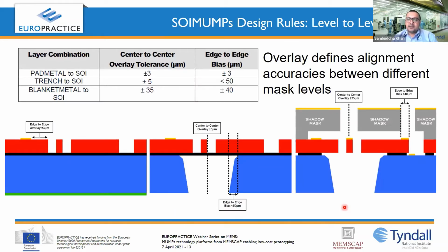There are also some level to level overlay design rules. Overlay means, as I already mentioned, that the top layer, the SOI mask, is patterned from the top side of the wafer. The trench is patterned by flipping the wafer, which means the alignment is done from the bottom. There could be an alignment tolerance or misalignment between the 2 layers. Therefore MEMSCAP says that a designer must keep in mind that for pad metal to SOI there could be a tolerance of plus minus 3 micron, whereas blanket metal to SOI could be of the order of 35 micron.